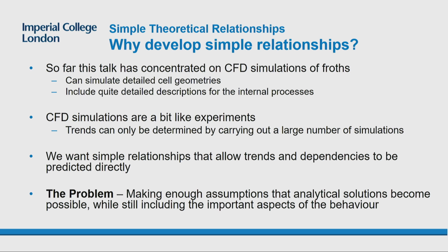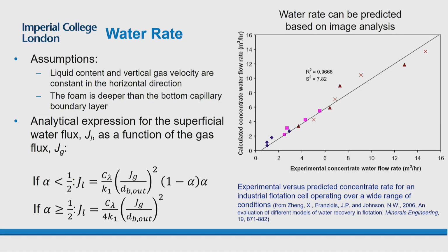So can we actually write out an equation for the performance based on the operating parameters? And the trick there is, can you make enough assumptions that you can actually solve the sets of equations while keeping in enough of the physics that the results make sense in terms of the behavior? The first one we did was looking at whether we can predict the amount of water we put in. We had to make some assumptions, such as that the liquid content didn't vary in the horizontal direction, it just varied vertically, and that the froth is much deeper than this capillary boundary layer.